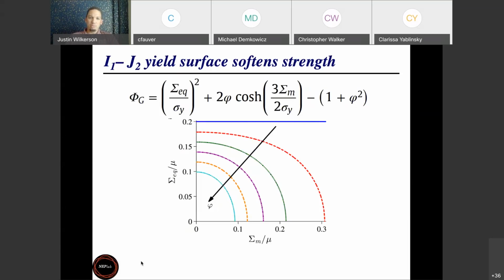So typically we will make use of some type of yield surface to account for that. The one that we make use of the most comes from the family of the Gurson type models, which you could call an I1 J2 yield surface. It depends on the von Mises stress, or J2, and it depends on the mean hydrostatic pressure, or I1, of the stress tensor. Those two stress invariants become the most important. And then the softening of the material as a function of porosity is accounted for through these yield surfaces here.